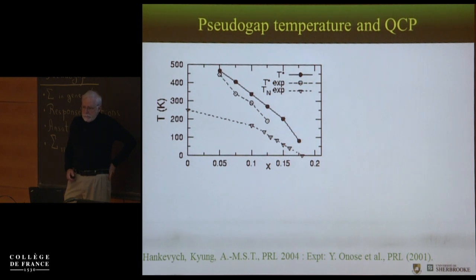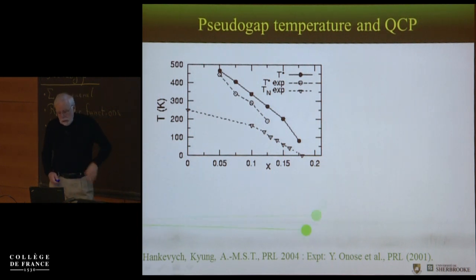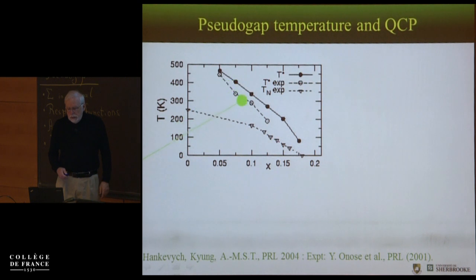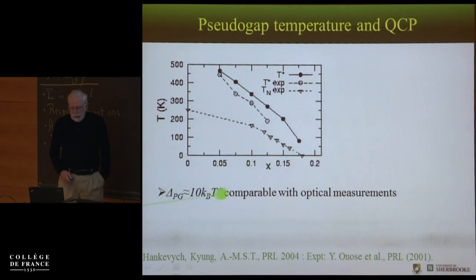Isn't it somewhat surprising that a small change in U value can produce such a big change? Well, it all depends on whether you're on this side of that line or that side of that line. We did the calculation at 200 Kelvin. Here is the temperature at which, in these calculations, the pseudogap appears, the solid line. This is the optical pseudogap, the dashed line, and this is where the antiferromagnetic correlation becomes infinite. So that's where the antiferromagnetic phase appears. In these calculations, the pseudogap is about 10 kBT star.